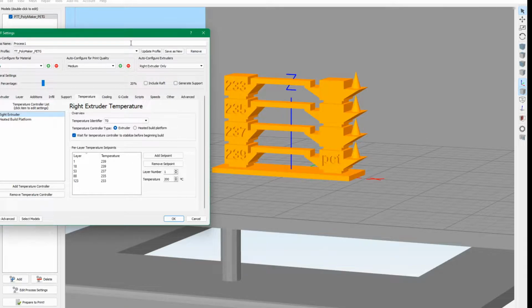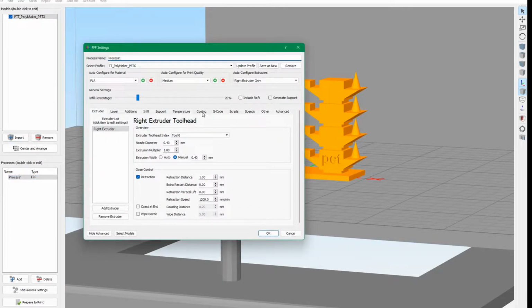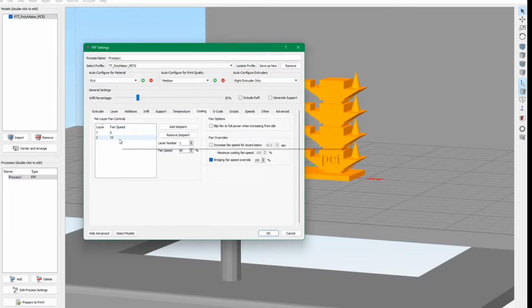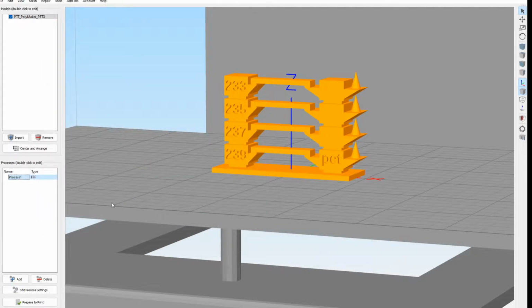So this looks like a good thing. It's only got four bridges, won't take very long. So we set this up. Oh, another thing I've been doing for all of my PETG is setting cooling at 10% after the first layer. The box says no cooling, but I have had problems with that. It ends up remelting the layer right below it. So I've had much higher quality PETG prints by having a little bit of cooling. I tried 25% and 20%, but 10% seems to be the best.